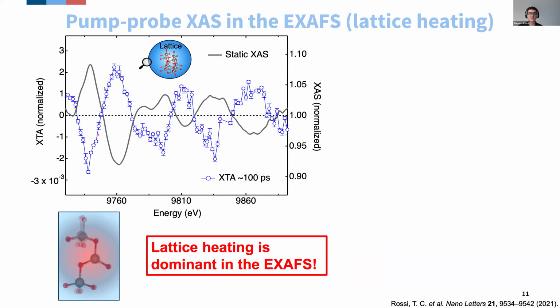So the pump-probe signal essentially looks like a mirror image of the equilibrium spectrum that's represented in gray. You can try to flip this spectrum along a normalized line, and you would see that they match pretty well. The message this is telling us is that immediately we know that what we are looking at is lattice heating, and that it's very dominant in the EXAFS.